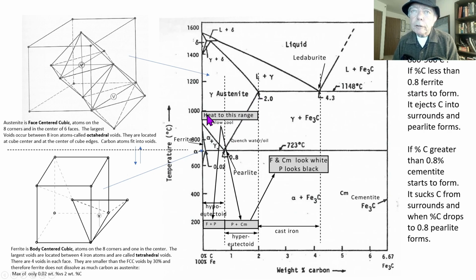Okay, now think about cooling. When you heat treat a piece of steel, you heat it up into this region, and then you cool. Now consider 2 ranges, less than and greater than 0.8. Less than 0.8, you cross this line, and ferrite starts to form, kicks out the carbon in between it. The austenite in between starts to rise in carbon composition. Eventually it hits 0.8 and you form pearlite. So you end up with ferrite and pearlite.